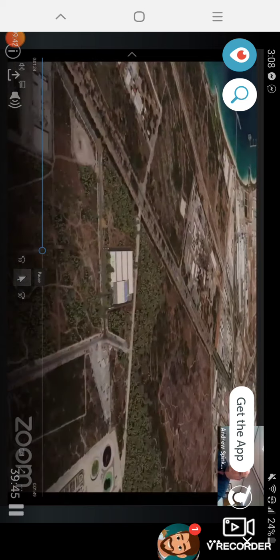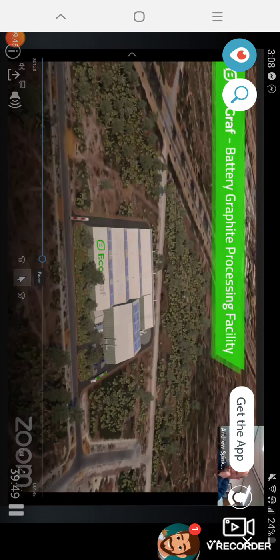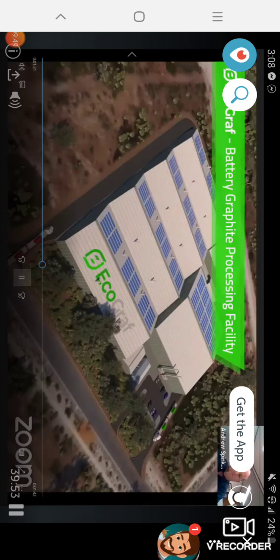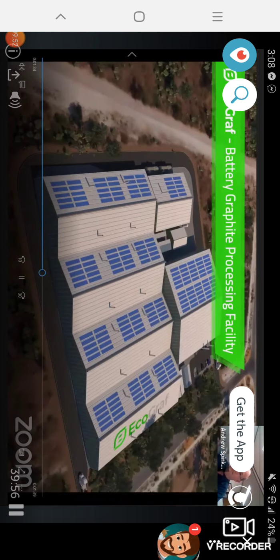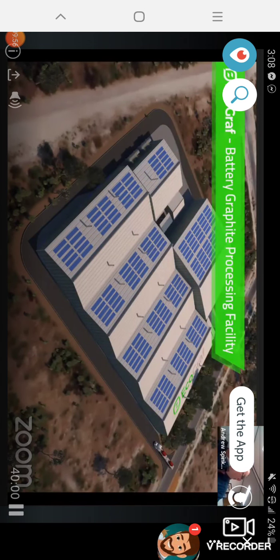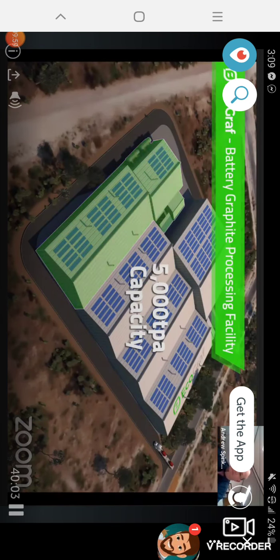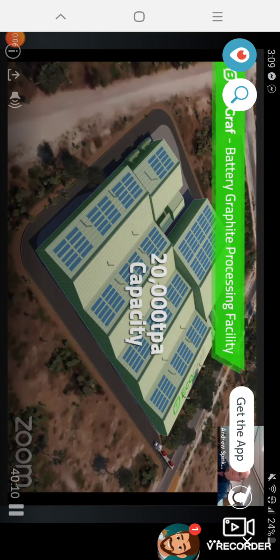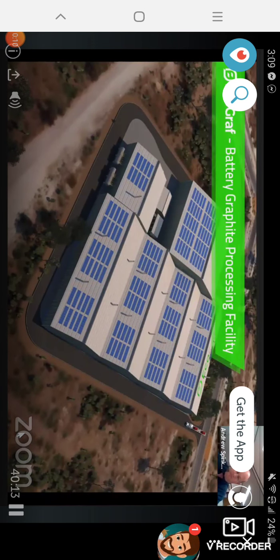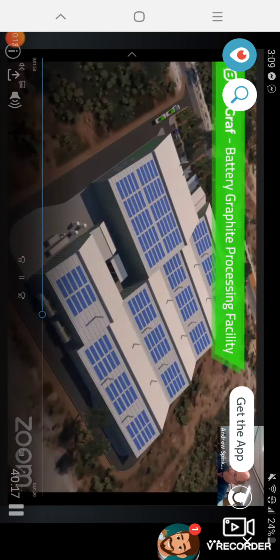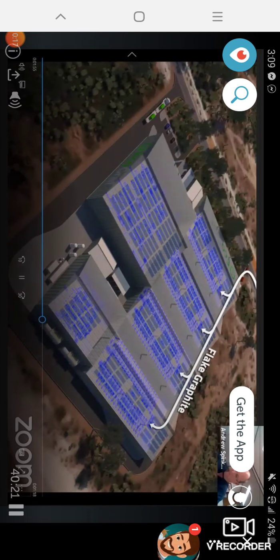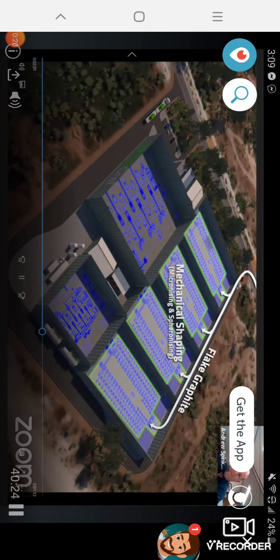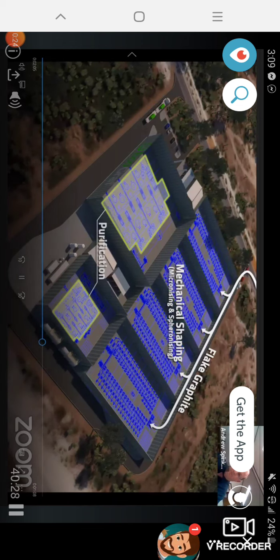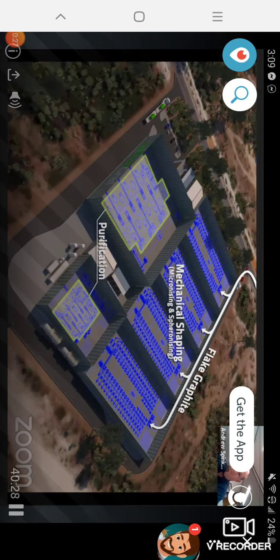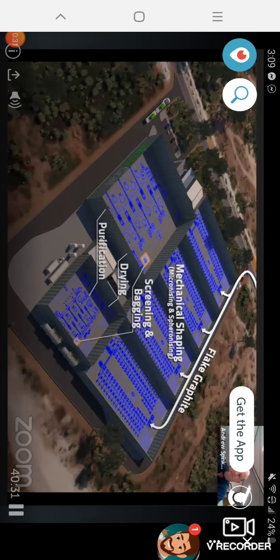Ecograph has invested substantially over the past few years to establish a unique and environmentally superior graphite processing technology. The proposed Ecograph facility will initially commence with a production rate of 5,000 tonnes per annum, followed by an expansion to a capacity of 20,000 tonnes per annum. The state-of-the-art new process plant eliminates the use of hydrofluoric acid and instead the EcoGraph process produces graphite in 2 stages. Firstly, the mechanical shaping of the graphite and then multi-stage chemical purification. The purified graphite is then dried and bagged prior to transport.